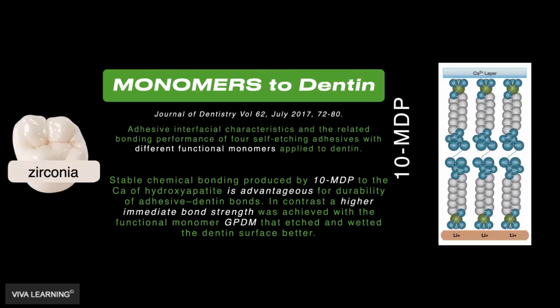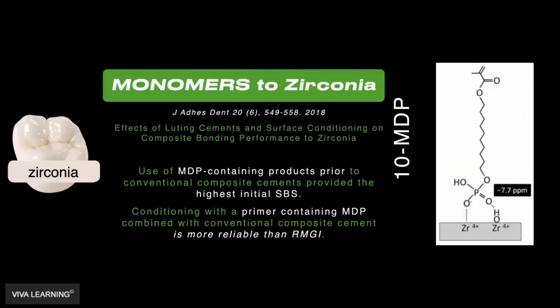Okay, monomers to dentin. This is the adhesive structure to the dentin. Different functional monomers, self-etching adhesives, right, with different functional monomers applied to dentin. Basically, they found that 10-MDP is great, and GPDM has even higher immediate bond strengths, because of the wetting of the dentin surface and everything else. So to the dentin, MDP, GPDM, both super good. Monomers to zirconia, they basically found that MDP-containing products provide the highest initial shear bond strengths, right? Way more reliable than a resin-modified glass ionomer, of course, because of the way that it functions. Okay.